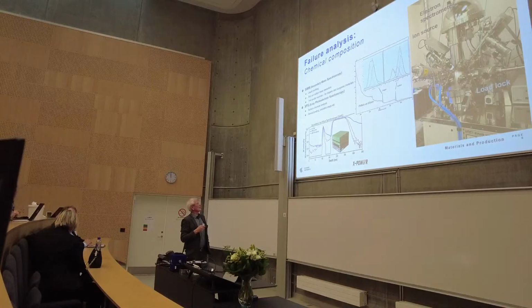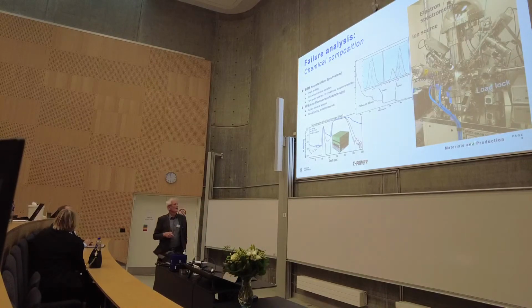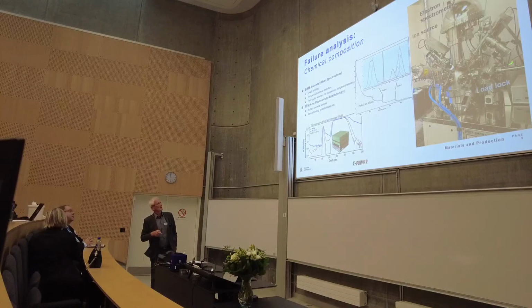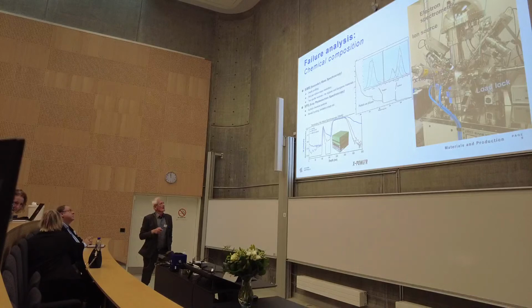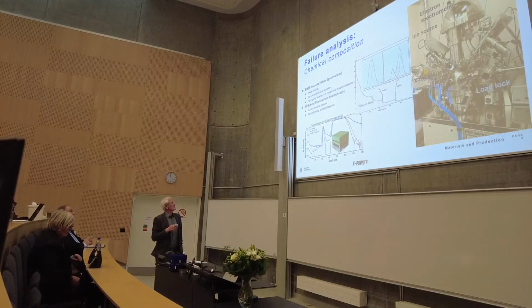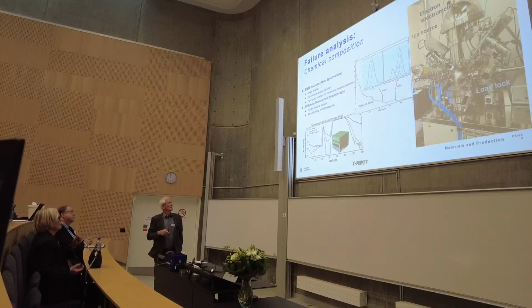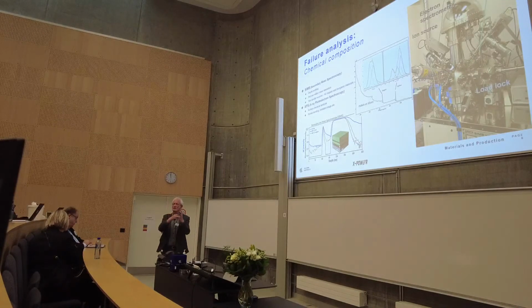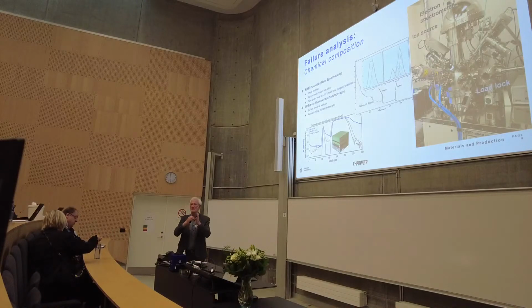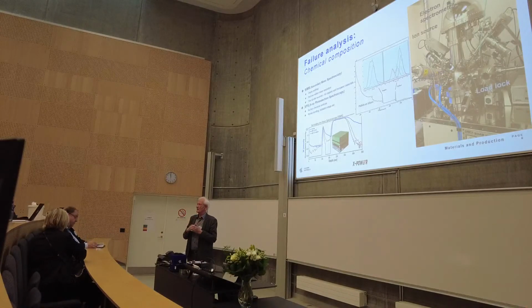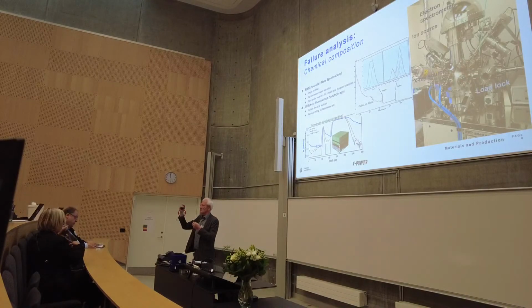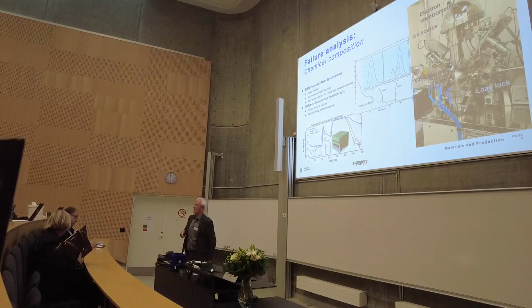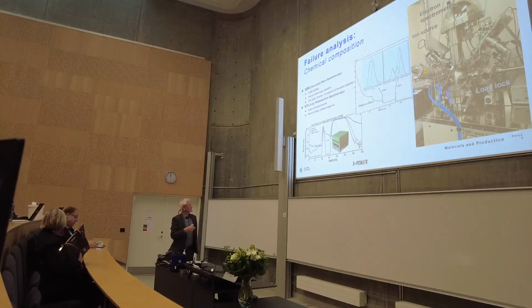Then there's chemical analysis. This system with things coming out in all directions is originally a secondary ion mass spectroscopy system where you can do depth profiling. So you send in ions. These ions knock out the ions of the material, and then you put them into a mass spectrometer. So you take their weight, and then you know what you have. And then you just sputter through the sample.